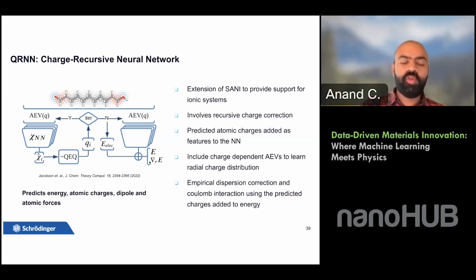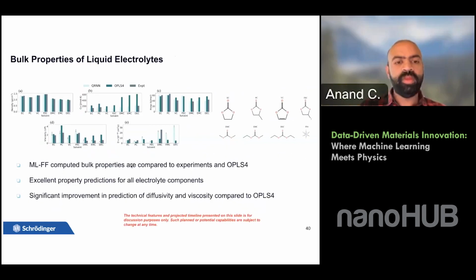And with this approach, we're able to perform machine learning force field simulations on lithium-ion battery materials, for example. When you have a lithium-ion cation and an electrolyte, these systems are quite complex and they are charged. So having a charge recursive neural network is extremely important for these types of properties. As an example here, we simulated the bulk properties of certain liquid electrolytes using our QRNN machine learning force field, and we compared it with OPLS and experimental data points. So here are some of the properties that we calculated: density, heat of vaporization, viscosity, and the diffusion coefficient.